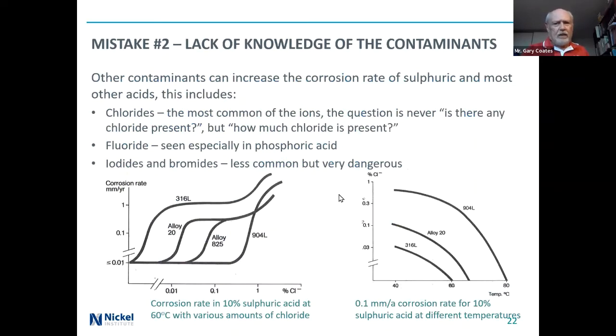Other contaminants can increase the corrosion rate, and I'm using sulfuric acid as an example here, but most other acids, chlorides, and we can see here, and this is tests I did years ago, in 10% sulfuric acid at 60 degrees C, 316L was actually passive with zero chloride in the reagent grade sulfuric acid at 10%. But the moment we added just a tiny amount of chloride, the corrosion rate went from almost nothing up to 1 millimeter a year very quickly.